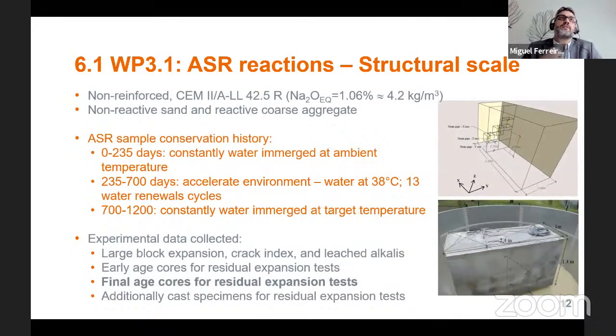So here is some background into the initial part of the project regarding these large concrete blocks. We see the type of cement that is being used, the sodium oxide equivalent, which is relatively high. We used a non-reactive sand and a reactive coarse aggregate. We wanted to achieve longer and greater expansions at longer times. Then we have a brief overview of what the conservation history of the block for ASR was. So for the first 235 days, it was kept constantly in water and at ambient temperature.